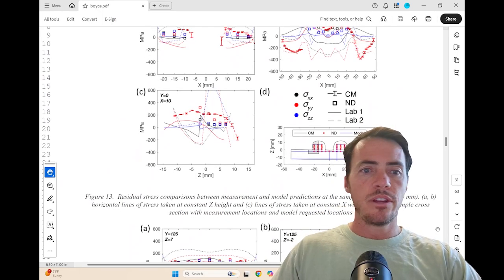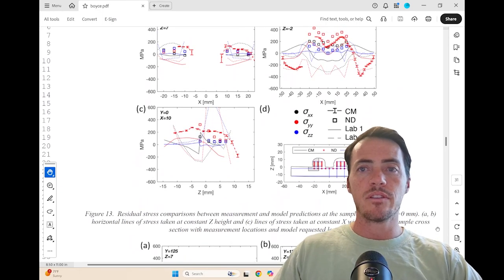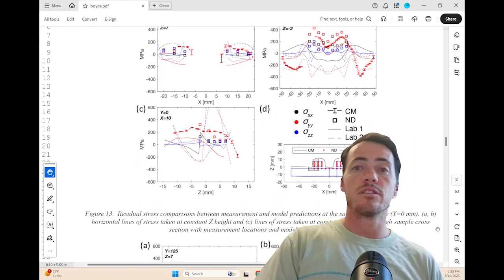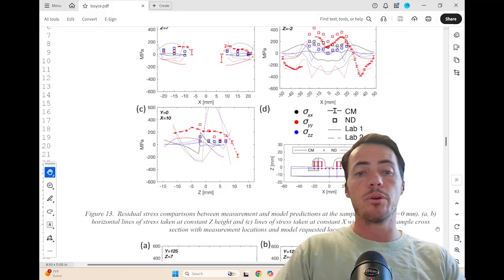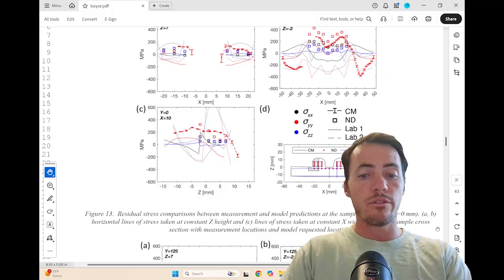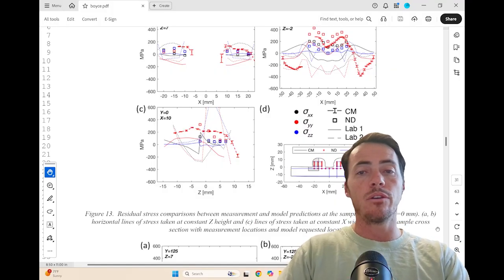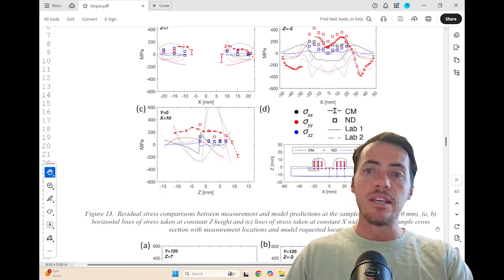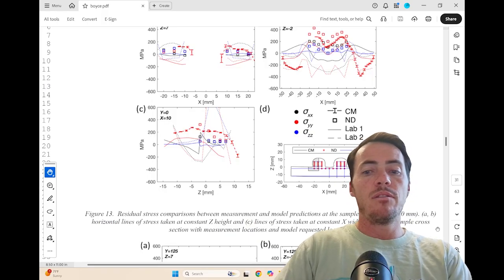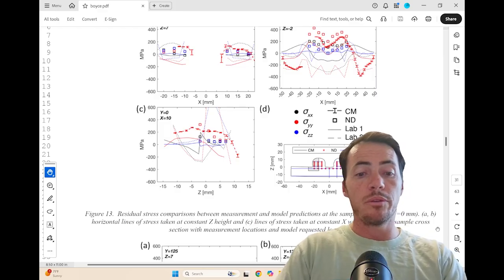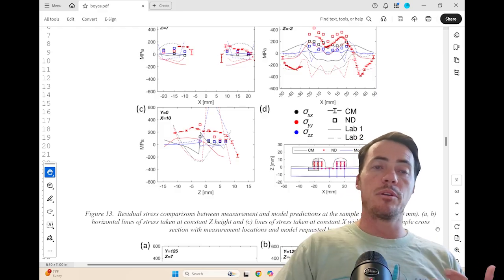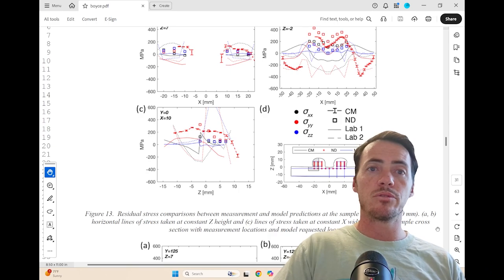Yeah, so down here we see the residual stress comparisons. They actually measured the residual stress experimentally, and they did so with two different approaches. One was using neutron diffraction, and the other was using the contour method. So you can see the CM and the ND data points here. And those both agreed with each other pretty well, which is good. That gives us confidence in the experimental ability to measure residual stress.